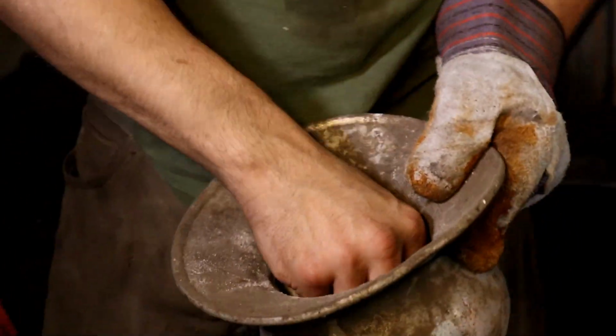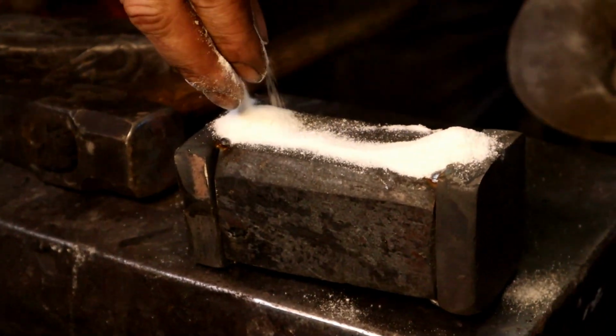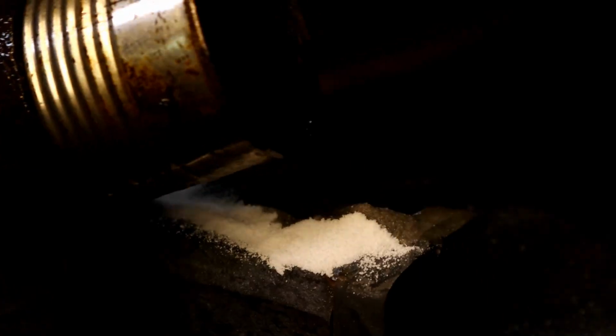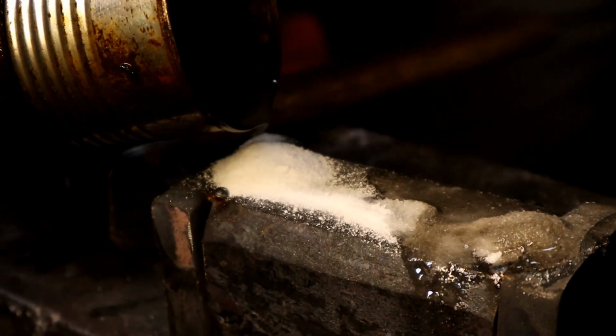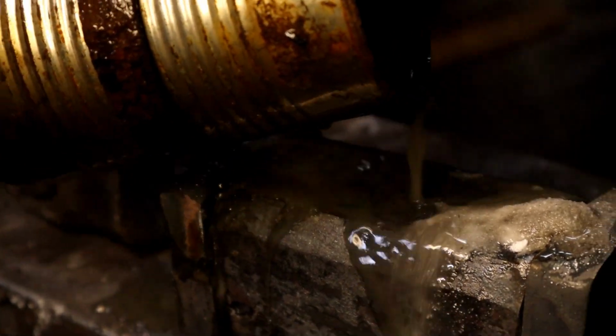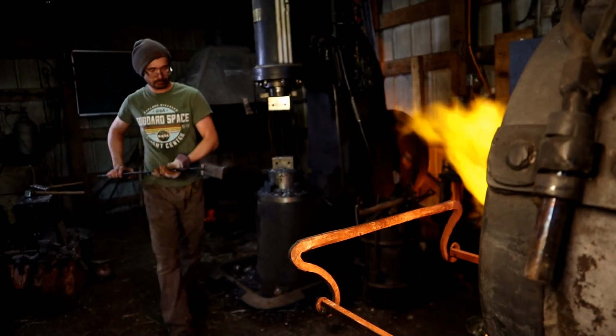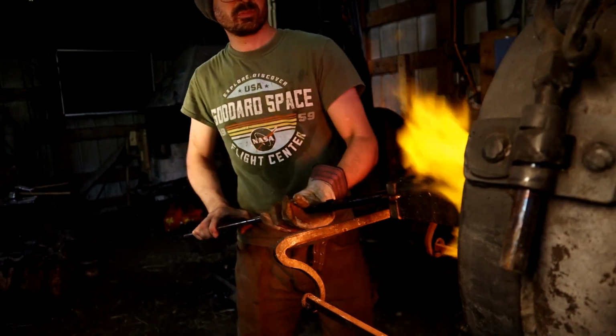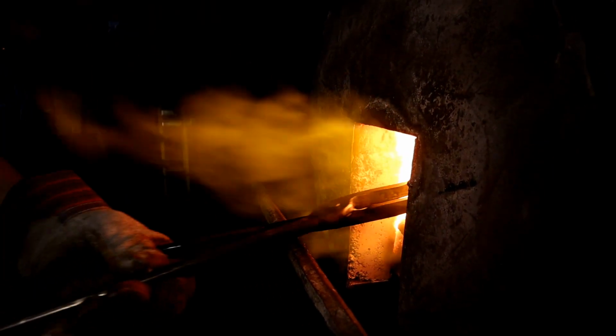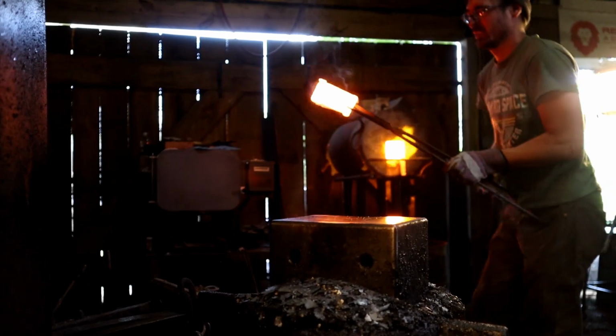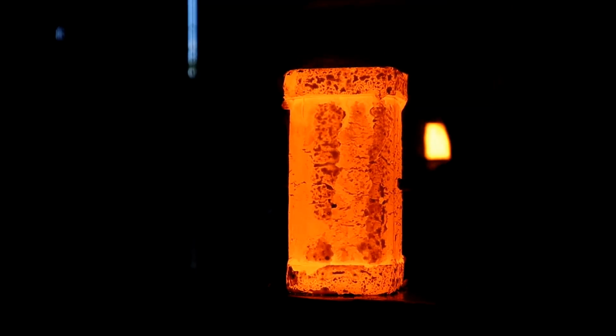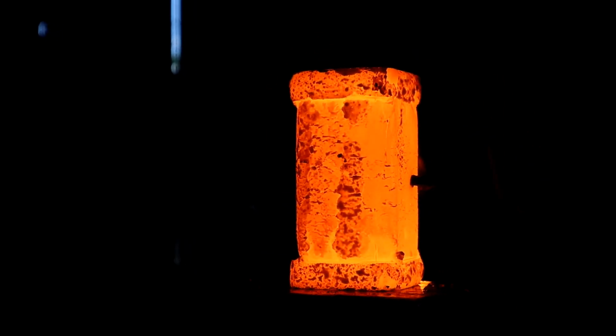Now that our material is tack welded together, it's time to add a little flux, in this case borax. As our material heats up slowly in the forge, the borax will melt, dripping down in between the material, creating an oxygen blocker, which makes sure no scale forms between our pieces. If that happened, it wouldn't be a good forge weld and our faces would fall right off the body of the hammer.